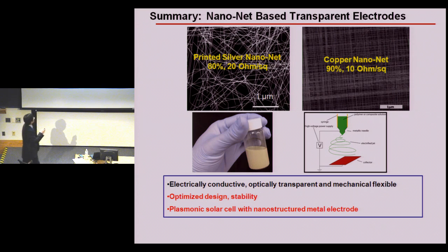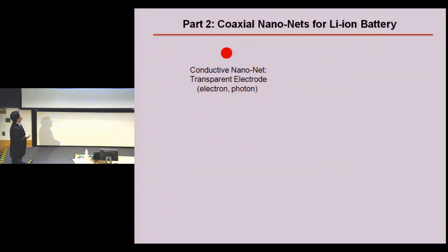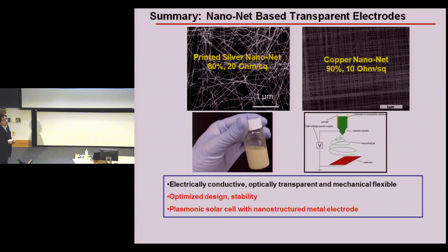What's the size of the nanowire? So the silver nanowire length is about a few microns, 5 microns. The diameter is about 30-50 nanometers. Copper is about 90 nanometers. And the length is, as I said, up to hundreds of microns.